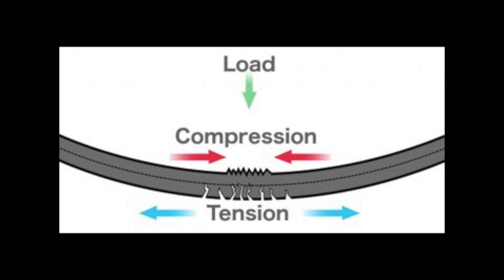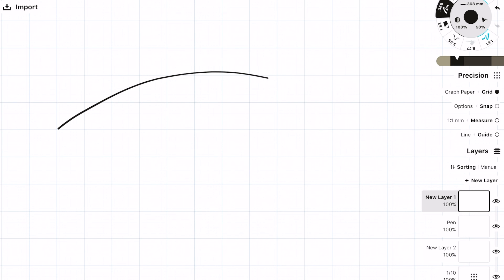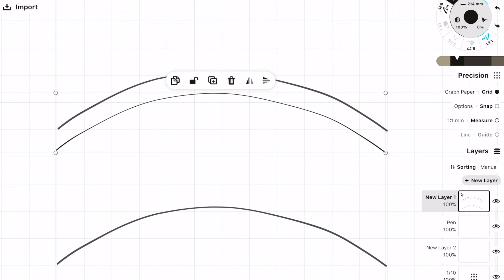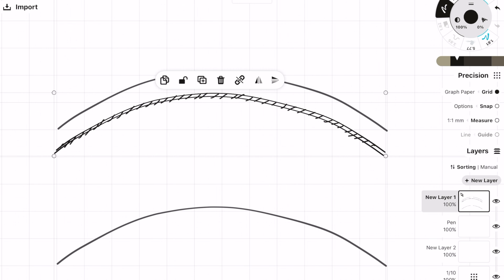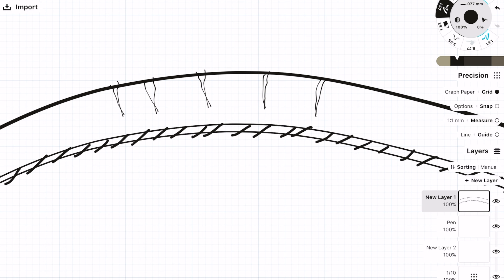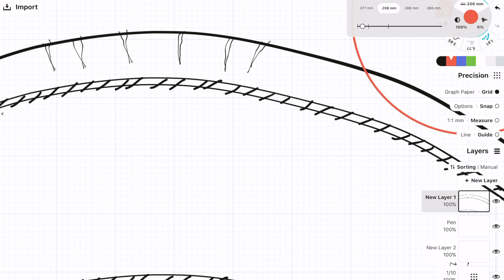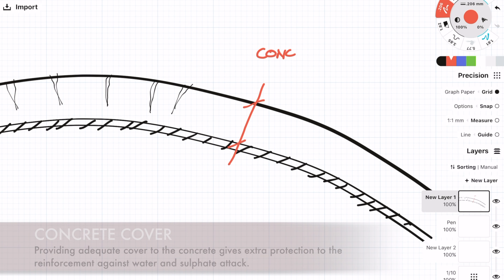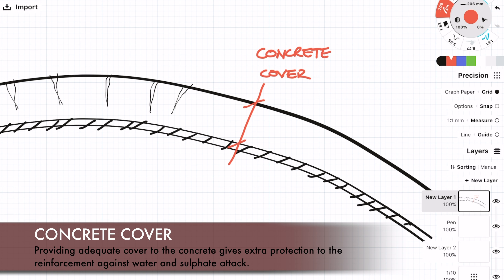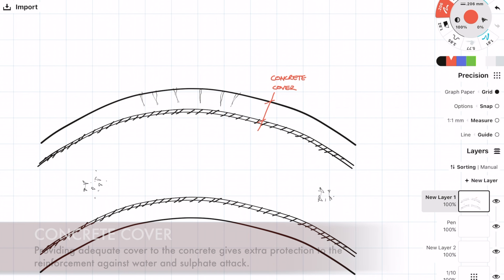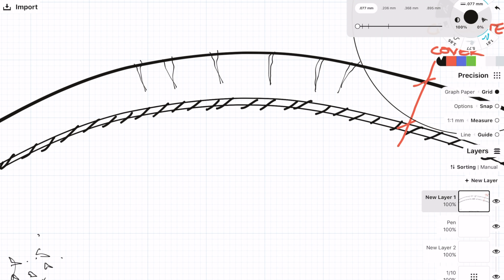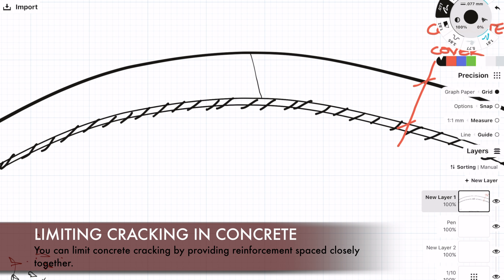It's really important to know that concrete structures are actually designed to crack, and concrete structures will crack — this is absolutely normal. Cracks will tend to form where there is tension. When we design concrete structures, we design to limit crack widths — essentially, we design to limit the size of the crack that can develop. The reason we want to limit the crack width is to limit the amount of water that can penetrate the concrete. Concrete is still waterproof even if there are small cracks, but we are talking crack widths of about 0.2 or 0.3 millimetres wide. What also helps protect the reinforcement is what we call concrete cover — the concrete from the edge of the element to the reinforcement. Limiting crack widths to 0.2 or 0.3 millimetres means the crack won't propagate deep enough to go beyond the concrete cover and corrode the reinforcement.